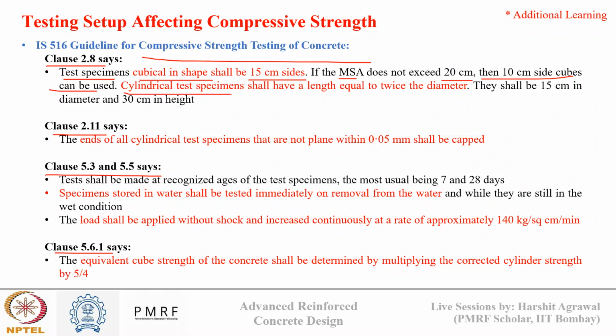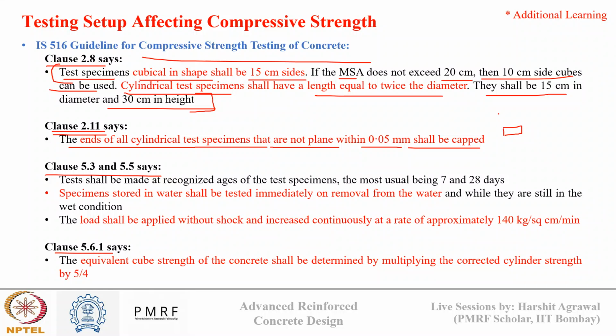If cylindrical samples are used, they shall have a length equal to twice the diameter, and they shall have a 15 cross section, 15 in diameter and 30 in height. So these are different specifications this clause is mentioning for the size of concrete. Then in clause 2.11, it is mentioned that ends of the cylindrical sample that are not plane within 0.05 mm shall be capped. So capping is done if the surface is not plane.